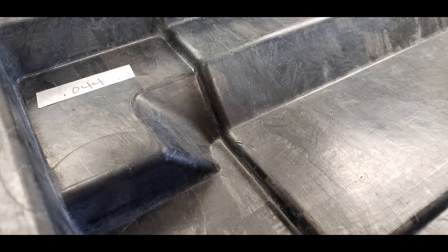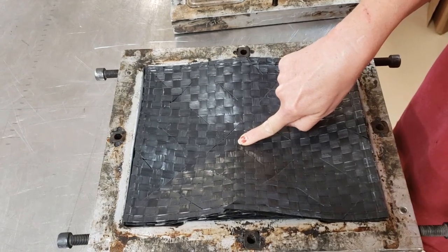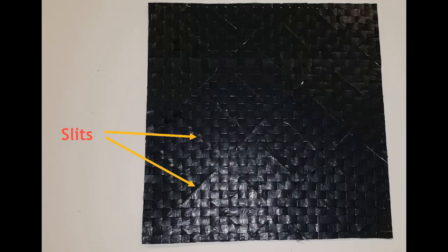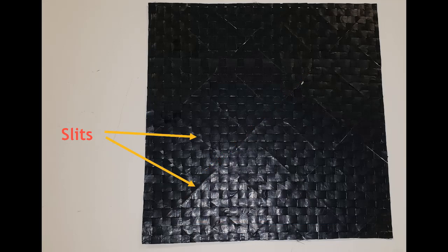The low flow method also minimizes flow fronts and fiber bunching, which are weak areas during the pressing cycle. Another key advantage of FiberFlex SMC is made possible by the FiberFlex woven fabric. The woven structure fixes the tows in two directions — 0 and 90 degrees. The slit pattern can be customized to manipulate how long and free the fiber coupons are, altered in different areas of the charge and from layer to layer. The slits are made at 45 degrees to the warp tows of the fabric, which allows the fabric to maintain a substantial amount of its integrity.